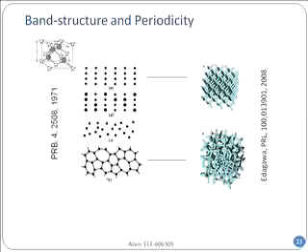In the amorphous case, sometimes you have a ring of 5, sometimes you have a ring of 3. In the regular case, you always have a ring of 6, but you never have a ring of 8. So amorphous is a little bit away from the periodic crystal, but not dramatically so. That is why even in amorphous silicon, or amorphous silicon dioxide, band gap is still a completely valid concept, right?